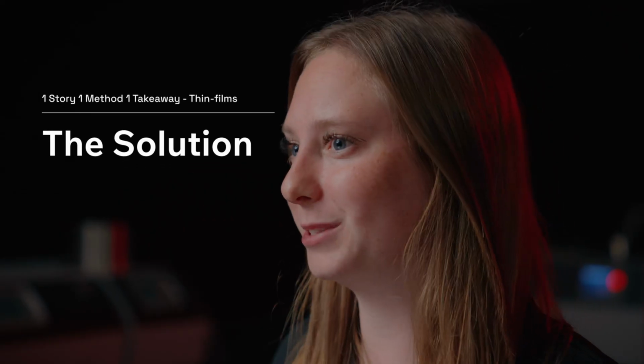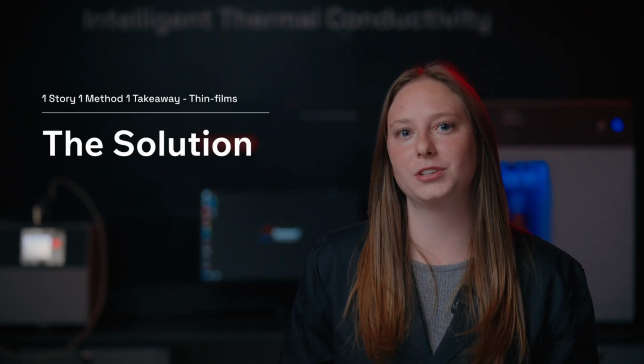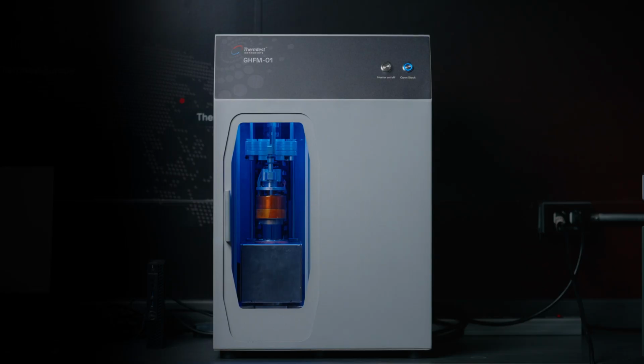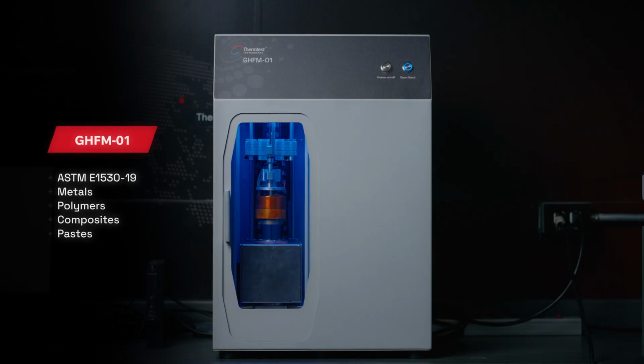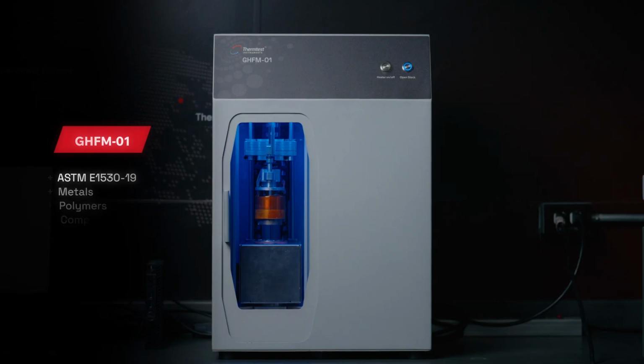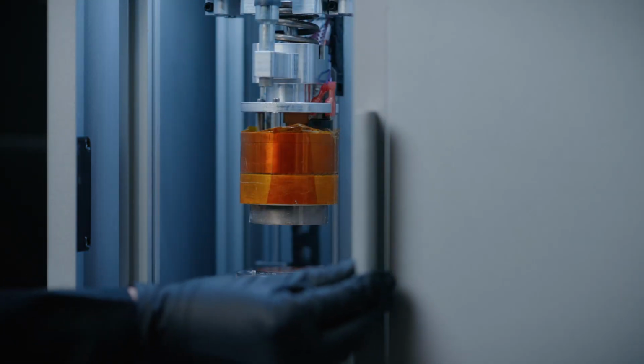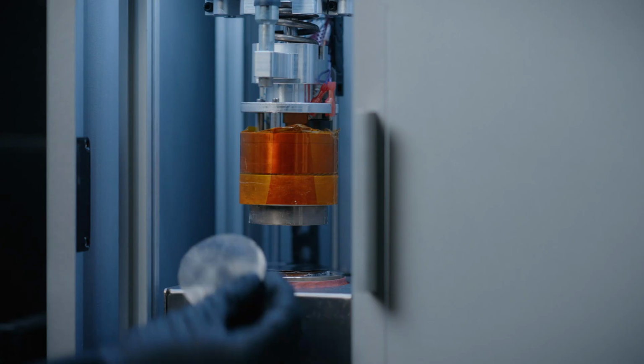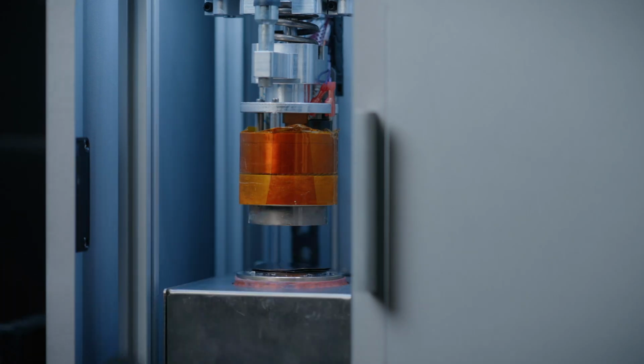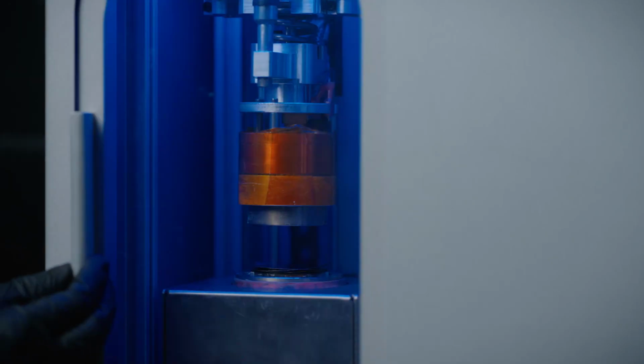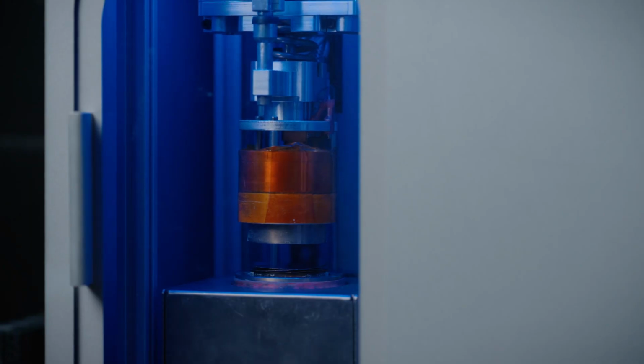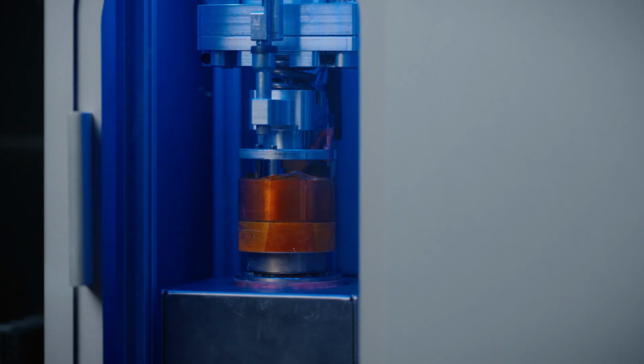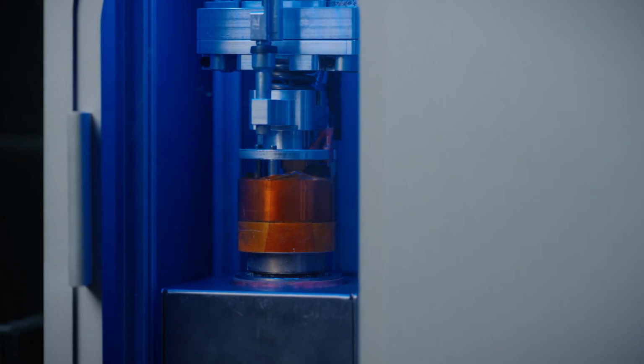That's where the solution comes in. The team turned to the Thermtest guarded heat flow meter, the GHFM-01. Following the ASTM E1530-19 standard, they set up a layered test method, stacking the graphite sheets in progressively thicker assemblies from 5 up to 23 layers. They built a linear relationship between sample thickness and measured thermal resistance.